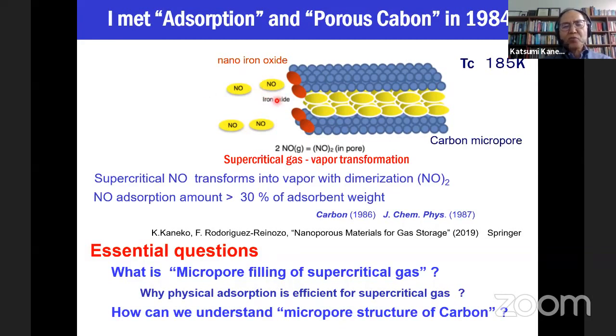N2O2 dimers. Nitrogen monoxide at room temperature is a supercritical gas, very difficult to adsorb, very difficult to condense on the surface or in pores. But once the nitrogen monoxide converts to the dimer, the dimer is a vapor. So spontaneously, nitrogen monoxide is condensed in small pores. Then this behavior changed my life. The materials can adsorb plenty of nitrogen monoxide, more than 30% of 1 gram of the adsorbent, almost corresponding to silica gel for water.